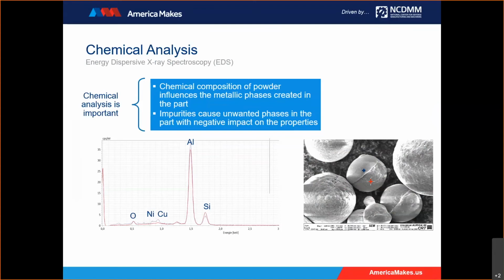So in this image on the right, you can see an example of elemental analysis on a powder particle with a cap. And on the left-hand side, you can see the spectra. The red curve shows a lower amount of aluminum and copper on the cap than the gray curve. And this difference in elemental concentration is due to the segregation during atomization, which isn't ideal because that can lead to inhomogeneity in the properties. So chemical analysis is important because it influences the metallic phases. The chemical composition influences those metallic phases that are created in the part. And so if we have any impurities, we get unwanted phases in the part that can have negative impact on the properties.